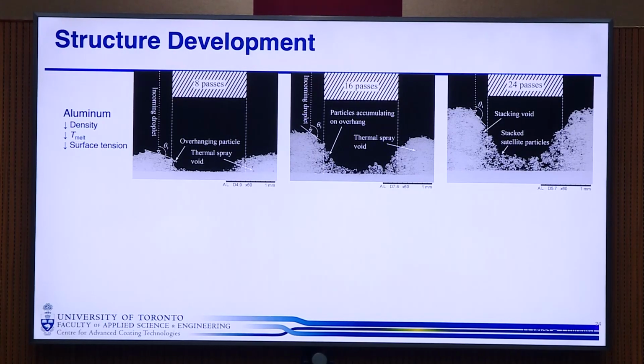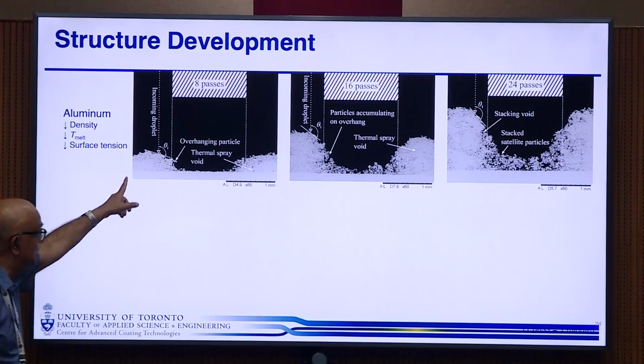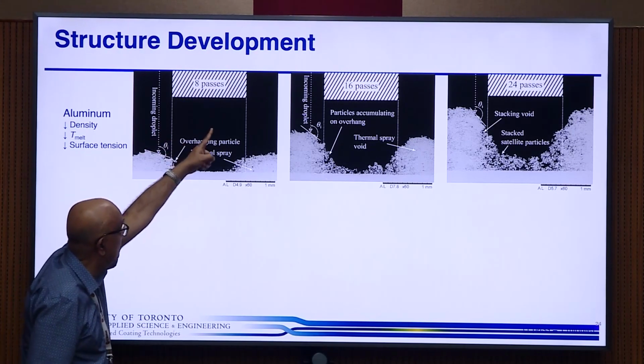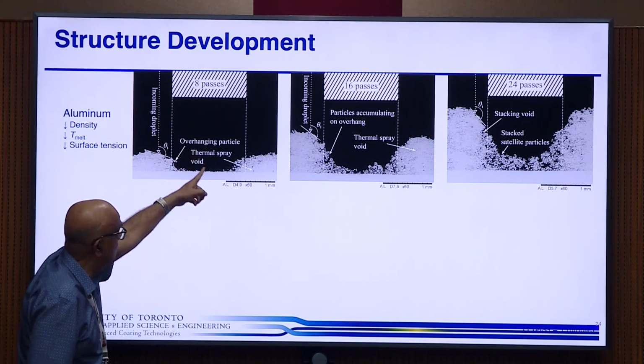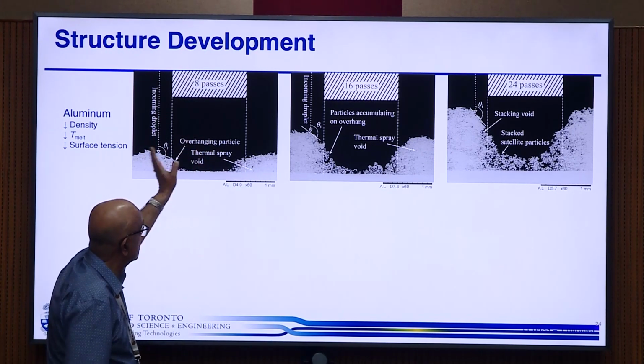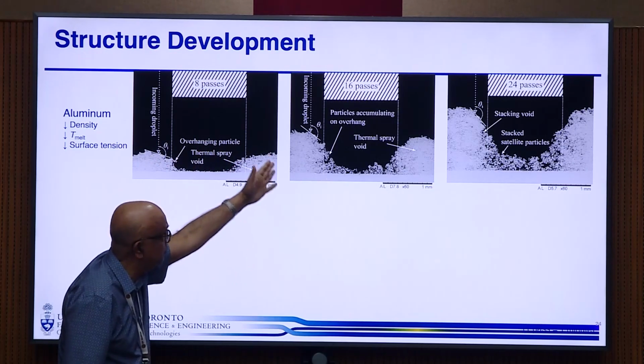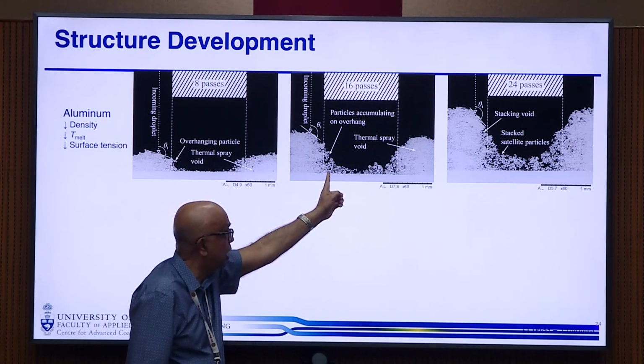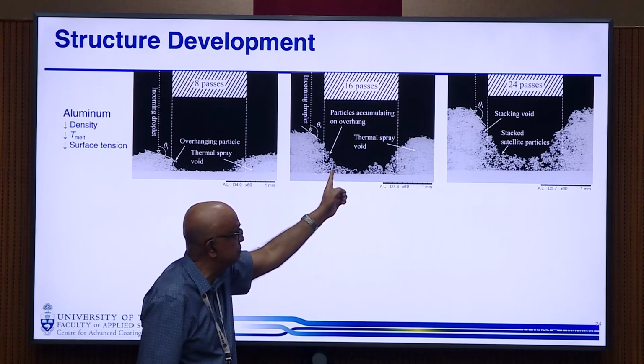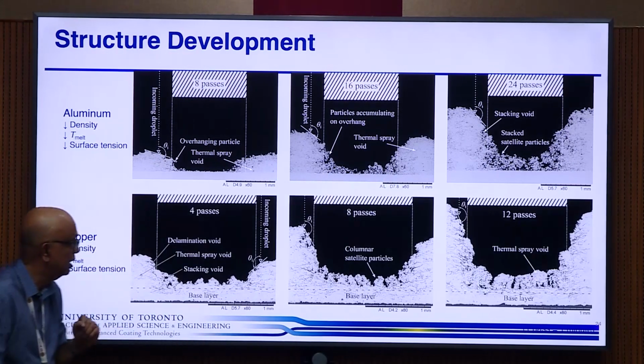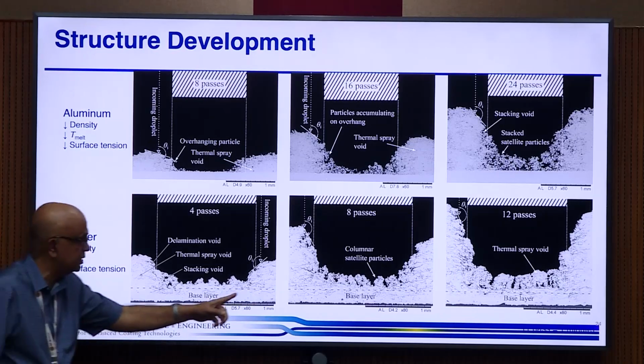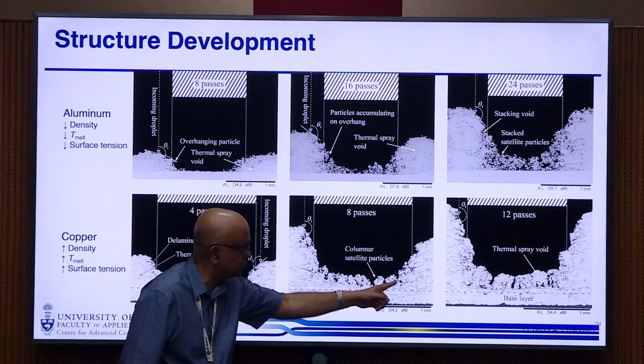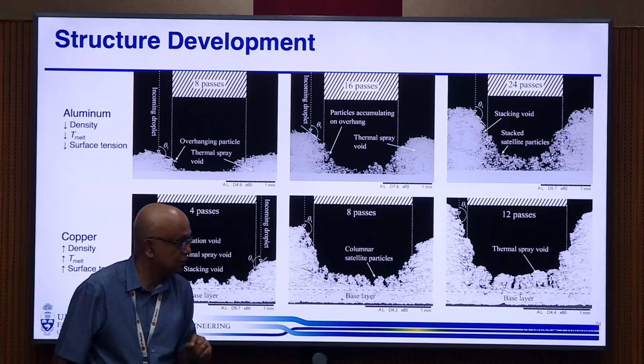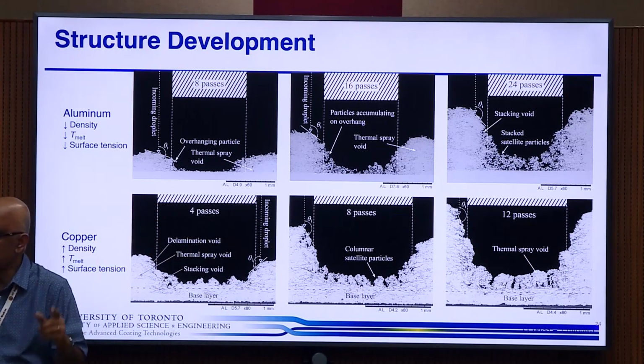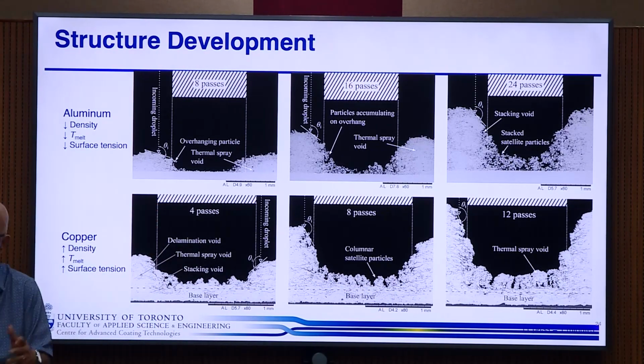Okay, so just to show, for example, with aluminum, this is the mask. We can think of the mask being over there. After 8 passes of our spray gun, you sort of grow these, and now these are satellite particles in the region between them. And we can do this with copper as well, and you see a columnar structure growing. So people have been trying to make structures. We actually just grow these structures as part of the process.